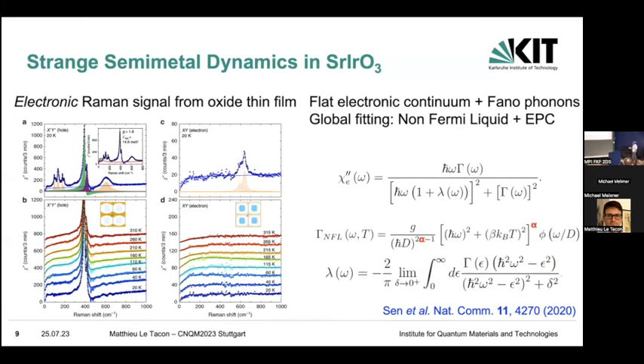So once we removed the boring phonons and kept just those ones, we implemented a global routine to fit this, which was widely used, for instance, in the cuprates, where you have to take into account especially the electron-phonon coupling. But here, the novelty was to do it without making any assumption on the type of dynamics of the electrons. So Jorg nicely wrote for us the response function of a non-Fermi liquid in the general case. If this alpha component here is 1, you get a Fermi liquid. If it's 1/2, you get a marginal Fermi liquid, and you can use it basically as a fitting parameter using a memory function response formalism, and you can get very good fits of those data. Long story short, what you get out of this is the scattering rate and the effective mass renormalization.